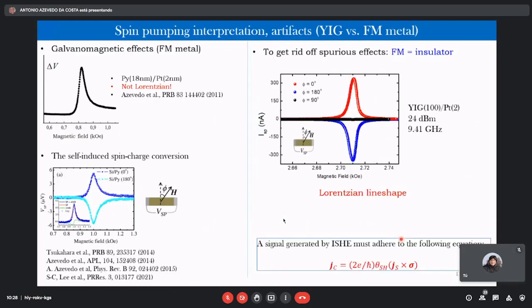So let me go quickly to this slide. What I would like to show you here is that making spin pumping measurements is tricky if you are using ferromagnet metals. Ferromagnet metals normally have a component which comes from galvanomagnetic effects, so due to the self-induced spin charge current. So a good system to investigate the spin pumping should be made of a ferromagnet insulator, such as yttrium iron garnet, and a heavy metal material. So in this case, the spin pumping signal is very symmetrical, and we can get rid of this galvanomagnetic effect and self-induced spin charge conversion, which are present in ferromagnetic metals.